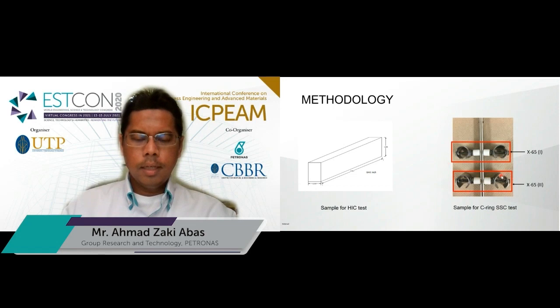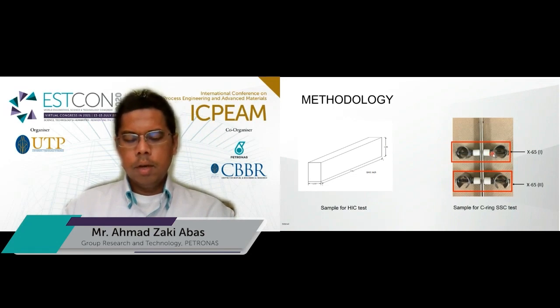For the sulfide stress cracking test, the sample looks like this. The sulfide stress cracking test specimen was stressed by tightening the bolt fixtures to the calculated deflection as measured by vernier caliper. C-ring samples were prepared with two stress levels, namely 80% yield strength and 90% yield strength.